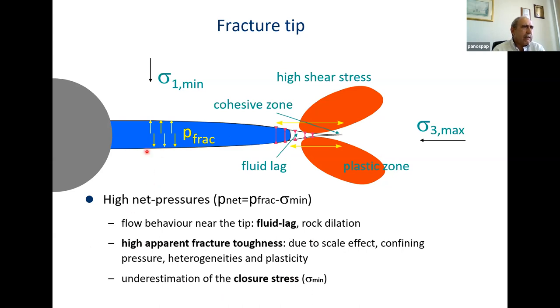To answer all of these propositions, we set up a finite element model. Actually, it was quite an advanced model with a modeling of hydraulic fracturing in the fracture, allowing for the formation of fluid lag. The model was also able to model plasticity in weak rocks near the fracture tip. Due to high shear stresses, we may have the formation of these plastic zones, as you can see here.